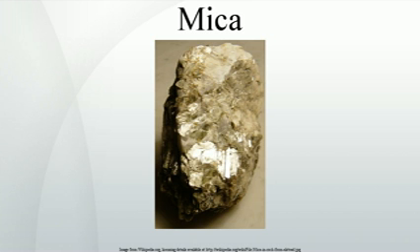Molding plate is also fabricated into tubes and rings for insulation in armatures, motor starters, and transformers. Segment plate acts as insulation between the copper commutator segments of direct current universal motors and generators. Phlogopite built-up mica is preferred because it wears at the same rate as the copper segments. Although muscovite has a greater resistance to wear, it causes uneven ridges that may interfere with the operation of a motor or generator. Consumption of segment plate was about 149 t in 2008 in the U.S.